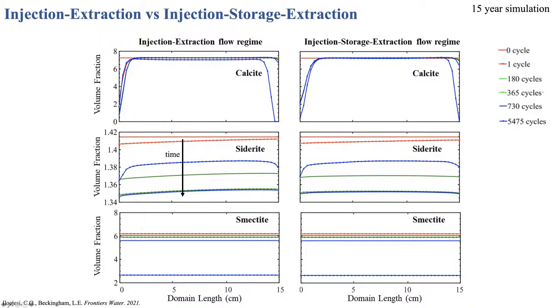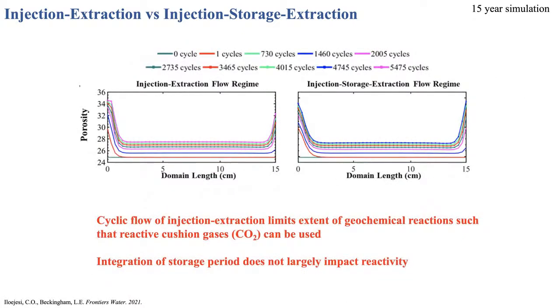If you're comparing that with the system where you have storage, you'll notice that these plots look really similar. We have some slight variations in the extent of calcite dissolution, where you have slightly more dissolution when you have storage near the injection well and slightly less further into the formation. Comparing then porosity evolution across the domain. The initial porosity here is about 25%. We can see near the injection well, you do get some pretty extensive increases in porosity up to about 35%. Also some increases further into the domain, but the majority of the domain here has much more limited increases in porosity.